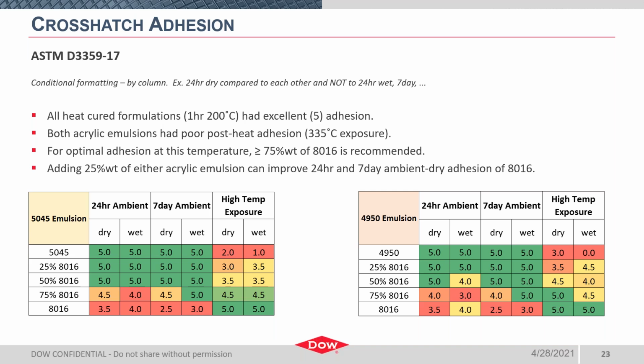This view gives a really nice illustration, in my opinion, of the obtainable performance spectrum, starting from that pure acrylic formulation, increasing silicone content, and then showing 8016 pure silicone-based formulation at the bottom. The color coding is done via conditional formatting by column. What this means is the 24-hour dry adhesion is compared to other 24-hour dry adhesion results in that column and is not compared to the 24-hour wet results or 7-day results, for example. And the trends observed were consistent between the acrylic binders.